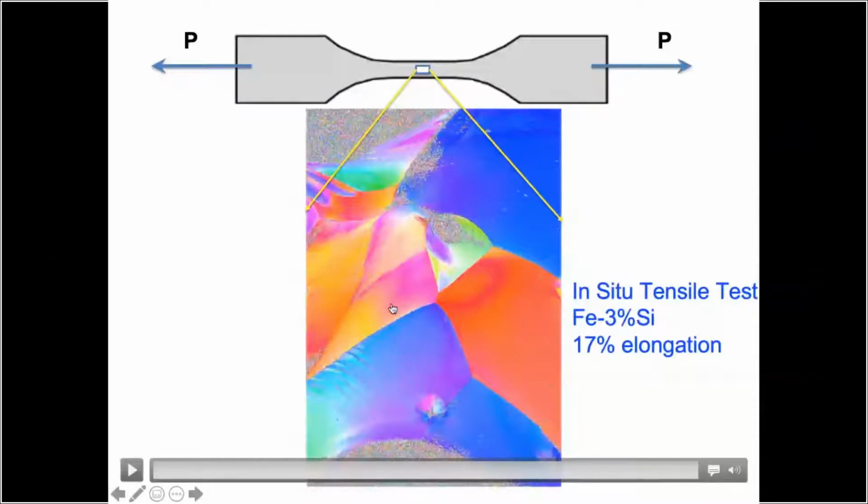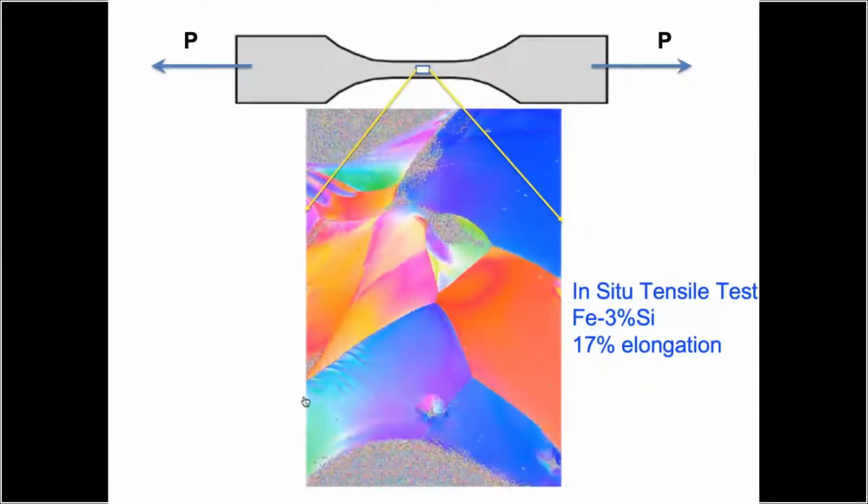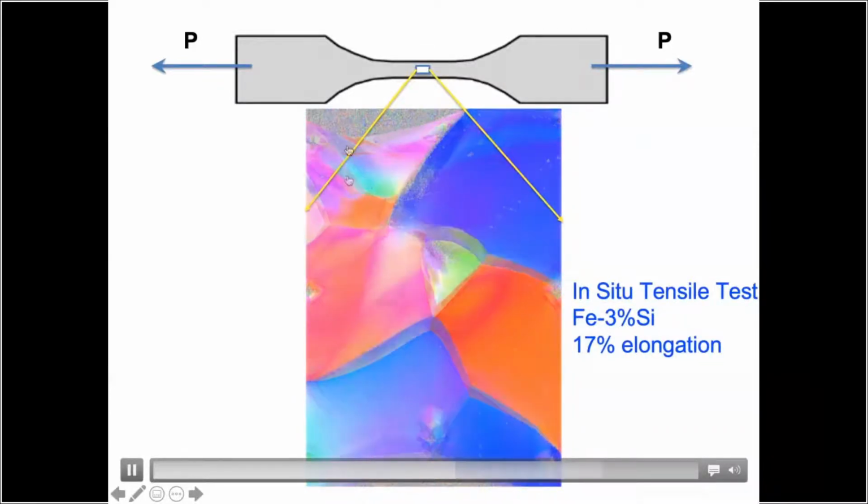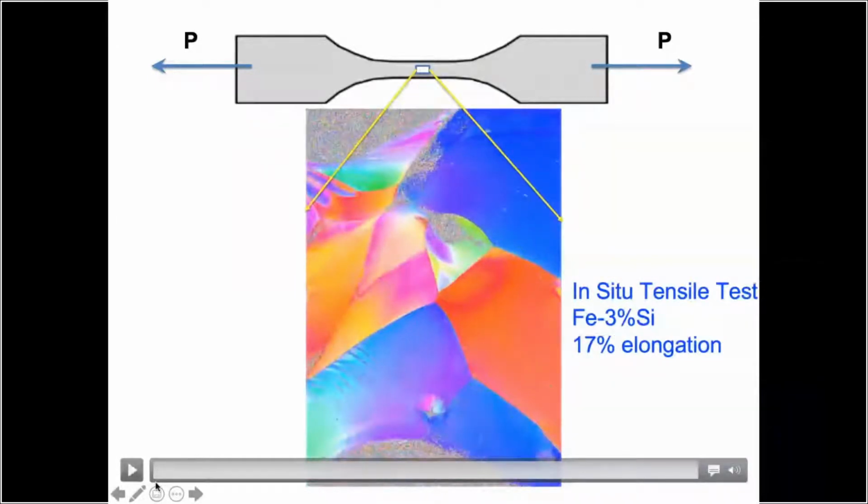And this gives rise to these accommodations at grain boundaries, to intense formation of shear bands and what we call strain heterogeneities. Also here, for example, you see a drastic split up of grains. You can see this here, how in the end you have different crystal orientations arising.